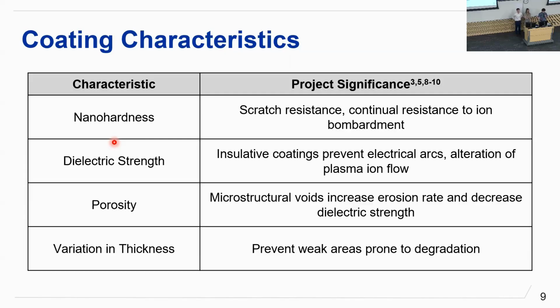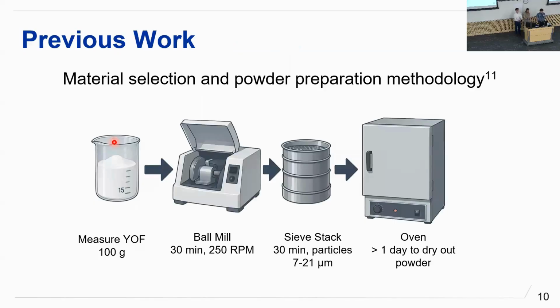having no weak points. So as Sam mentioned, NextEdge did sponsor a project last year, and so we're using that as a baseboard. And so, especially with their powder methodology. And so what we did is, or what they did that we're using is take the powder, ball mill it to reduce the particle size, separate using a sieve, and then bake out any moisture in the particles through the oven.